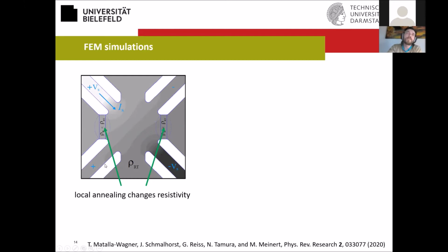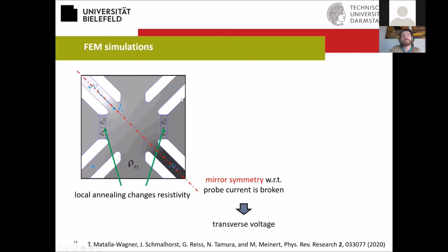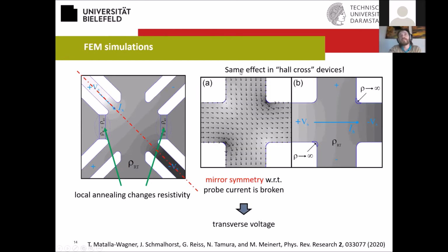You can see this here in the asymmetry, and we have some voltage buildup plus and minus here. This essentially comes from a broken mirror symmetry around this probe current. So when this mirror symmetry is broken geometrically, you immediately get a transverse voltage drop, which is what we observe in our experiments. Unfortunately, this is also present in simple Hall cross devices. Sometimes we do experiments with these simple devices, passing currents like this. Very much the same behavior.